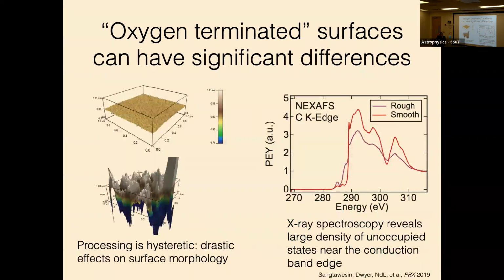Okay, so one of the things that we figured out almost instantly on this project is that a lot of the community talks about how you need oxygen terminated surfaces to stabilize NV centers, but when they say oxygen terminated, those can be very, very different types of surfaces. In particular, if you just have two slightly different starting morphologies and then put them through the exact same processing, you can get these runaway surface roughening processes that lead to extremely different final surface morphologies. And this is because a lot of processing in diamond is very hysteretic. So depending on where you started, you end up in very different places.